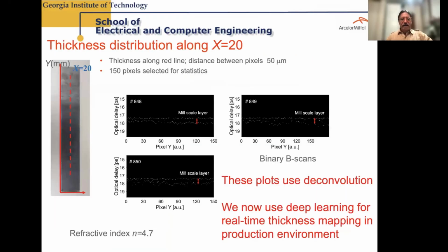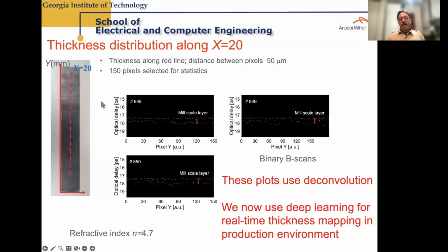So here's an example where these are measurements made down this dashed red line on this sample. And here you can see after some processing, we have two reflections. One is from the air mill scale interface, one is from the mill scale steel interface, and then we can extract the thickness of the mill scale. Okay, so we are scheduled to test this out on a production line for ArcelorMittal. So it's a real world technique that we hope will work in production.